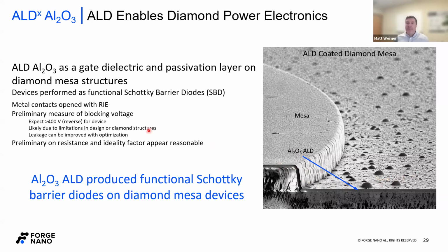And actually we're able to measure some properties, which was great. That means our ALD film was high quality, that it was well adhered. So even though diamond is inert, it looks like TMA water can do it. Of course, the breakdown voltage was lower than expected.